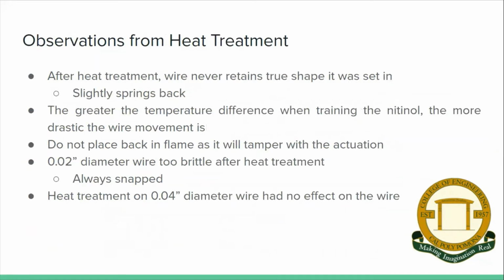There are a few observations noticed during the heat treatment of the nitinol. One being that after heat treatment, the wire never retained the true shape it was initially set in. It always slightly sprung back. Next is that the greater the temperature difference when training the nitinol, the more drastic the wire movement was. After heat treatment is complete, do not place back in the flame as it will tamper with the actuation when running a current through.